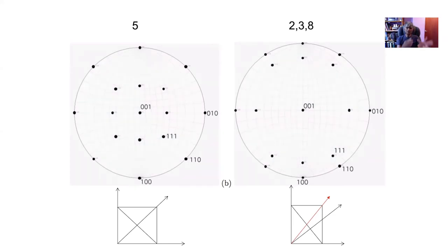the number at the top indicates a lattice parameter of 5 arbitrary units, okay? So a cubic stereogram doesn't change if I change the lattice parameter to 8, because we are simply plotting angles between vectors, and a cube is a cube no matter how big it is. So the angular relationships between the vectors are preserved. Now, if I change to an orthorhombic crystal with three different lattice parameters, the stereogram changes completely. So here we are plotting plane normals, okay? These are all plane normals. And because we have such an exaggerated difference between the lattice parameters, this stereographic projection looks nothing like this, okay?